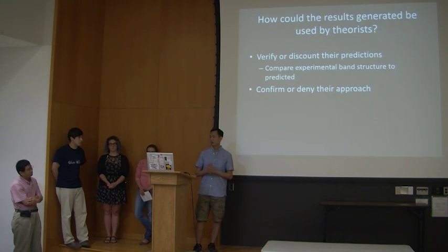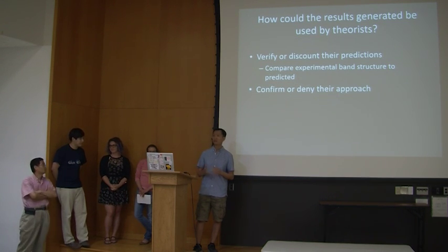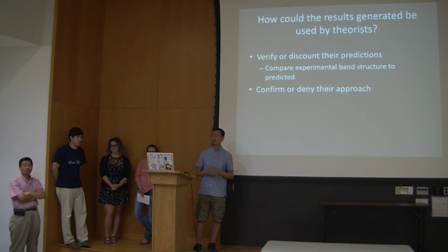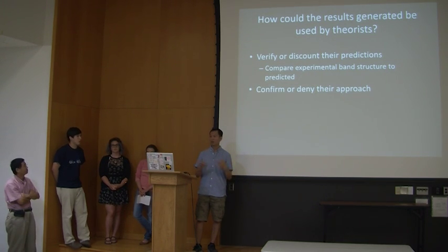The reason being is also that DFT results are mostly calculated at a temperature of 0 K. So whatever experiments we have done might not correlate directly to their structures. So using MD, which we can actually perform at higher temperature, we could do a much better job. But of course, sacrificing some accuracy, but at the same time, we could simulate a much bigger system, then we might be able to get a better agreement.